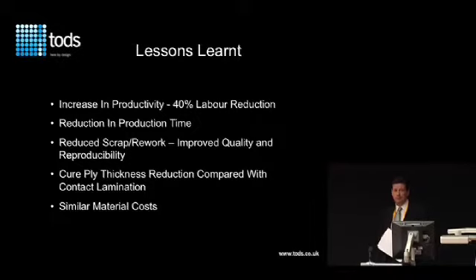Production time, again, because you're not going through all those stages, it's a far quicker process. It's not uncommon with sandwich panels that have been hand laminated to get dry patches and blisters. I think it's fair to say that just did not occur on any of these panels. One comment that I've had from other people rather than own experience is because the resin content is far lower, your laminate actually comes out a lot thinner. It's just a matter of taking that into account. And it's a similar materials cost to hand lamination, so your real saving is in your labour.